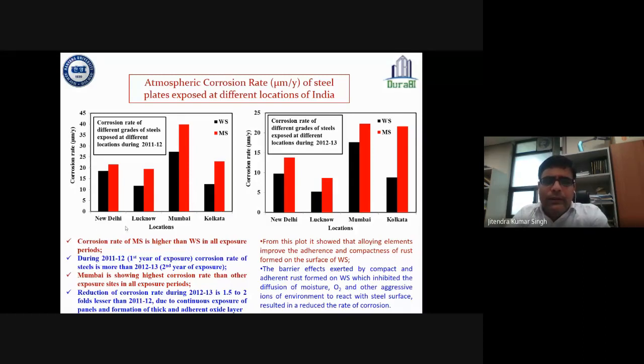So the red one is for the mild steel that doesn't have any alloying element like copper, chromium, and silicon. But WS, weathering steel, you can see always has a lower corrosion rate compared to the mild steel. It is due to the alloying elements. It means the alloying elements can improve the resistance to corrosion by the formation of corrosion product. Once the exposure period is increased, when the same sample is continued, you can see the corrosion rate decreased with the exposure time.